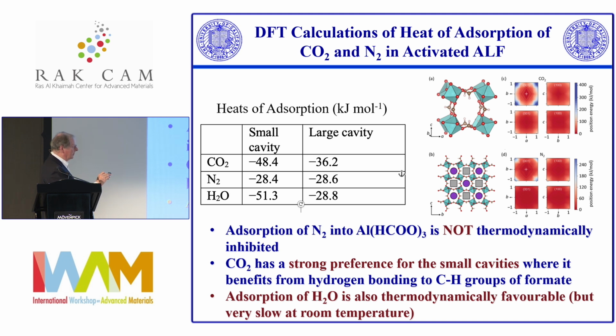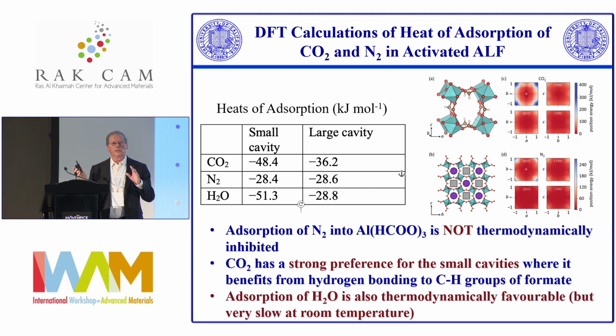And interestingly, water has a very favorable heat of adsorption, especially into the small cavity with its hydrogen bonding. But water goes in extremely slowly. We left a sample on the bench for 3 weeks at NIST, and then ran the neutron diffraction, and you don't see any change in the background. It just sat there, and it looked like it did when we first activated it. So it's very stable.